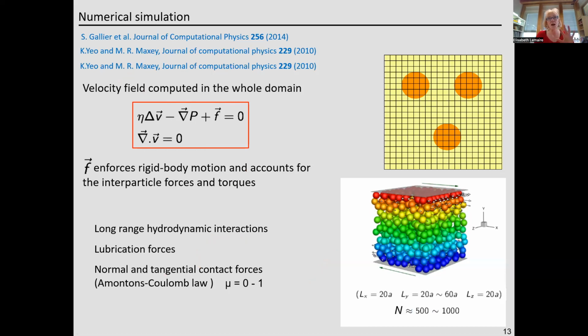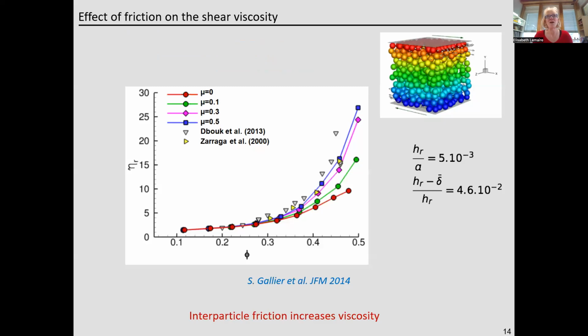I have no time to detail the numerical method, but you can ask Michel, who is a great specialist of that. I go to the result, and the result is that the viscosity of a non-Brownian suspension increases a lot when you increase the solid friction between particles. So here you have the variation of the relative viscosity, the viscosity divided by the viscosity of the suspending liquid, with the particle volume fraction.